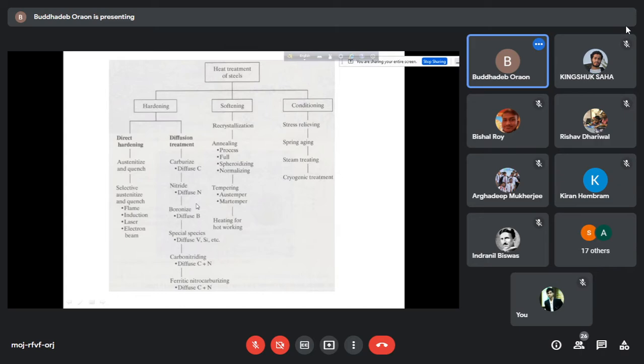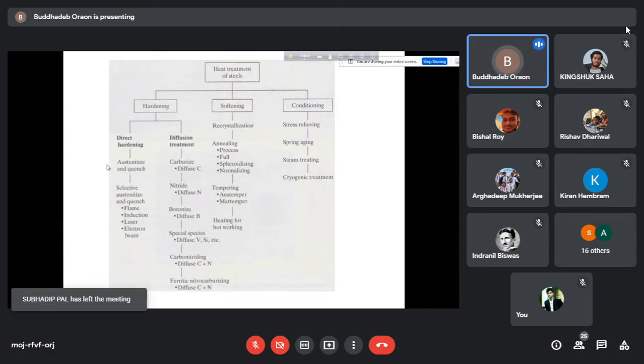Like hardening, we have direct hardening or diffusion hardening. In direct hardening, we have austenitize and quenching. By quenching, as we have discussed, with the appropriate cooling rate, we can increase the hardness of the material. Then selective austenitize and quench: flame hardening, induction hardening, laser hardening, electron beam hardening. So these are some of the processes.